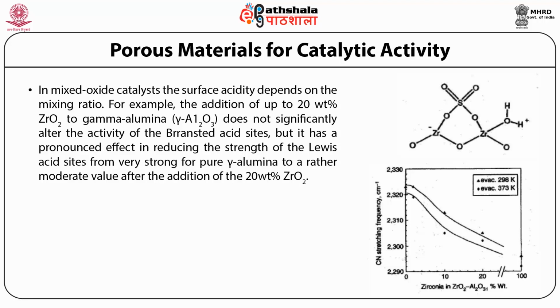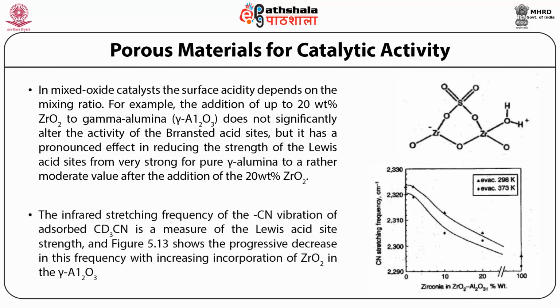In mixed oxide catalysts, the surface acidity depends on the mixing ratio. For example, the addition of up to 20% of zirconia to a gamma alumina Al2O3 does not significantly alter the activity of Brønsted acid sites, but it has a pronounced effect in reducing the strength of Lewis acid sites from very strong for pure gamma alumina to a rather moderate value after addition of 20% zirconia. The infrared stretching frequency of the CN vibration of adsorbed CD3CN is a measure of Lewis acid site strength. There is a progressive decrease in this frequency with increasing incorporation of zirconia in the gamma Al2O3.